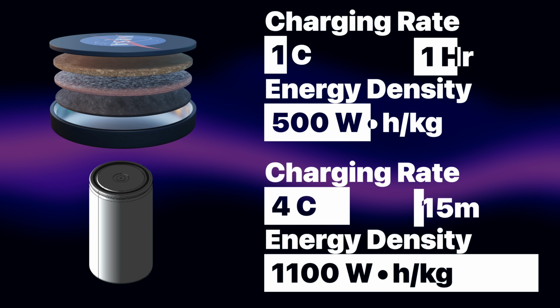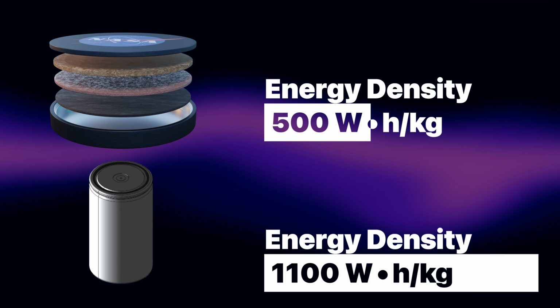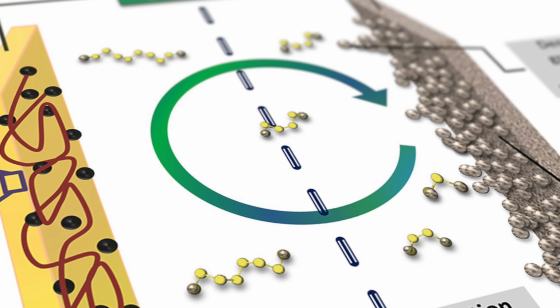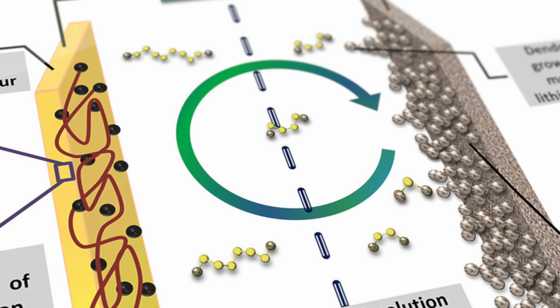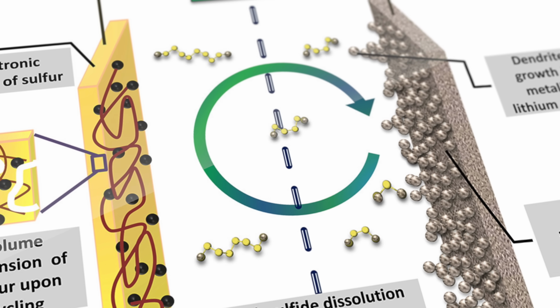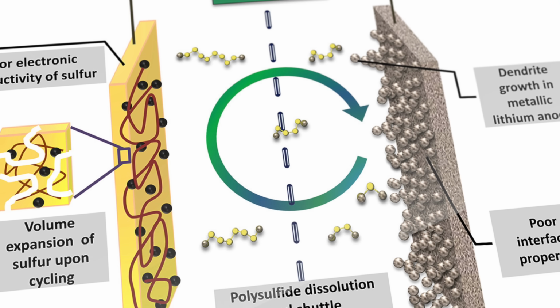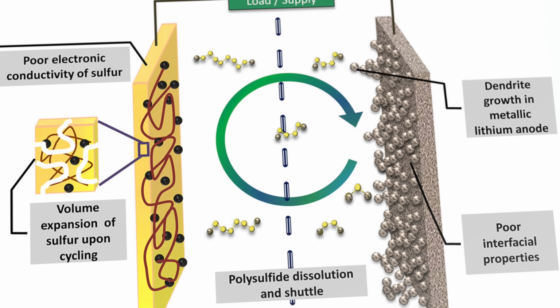So SABERS has roughly half the power density of one of the best lithium-ion batteries in the market, which is nothing to scoff at, considering that most older solid-state batteries had much less than 1/10 of that power. Another major drawback of the sulfur selenium battery chemistry is something called polysulfide shuttling, which reduces cycle life significantly. This happens when the sulfur in the cathode moves or shuttles through the electrolyte and to the anode.